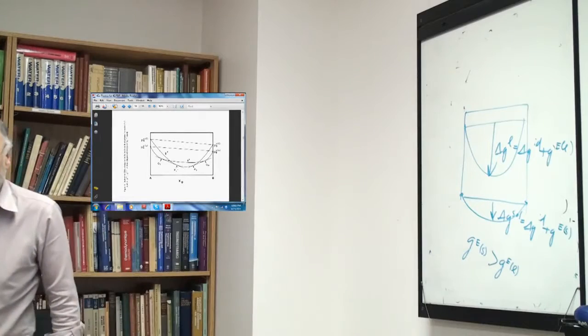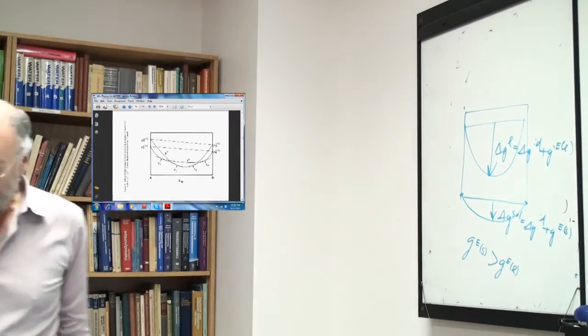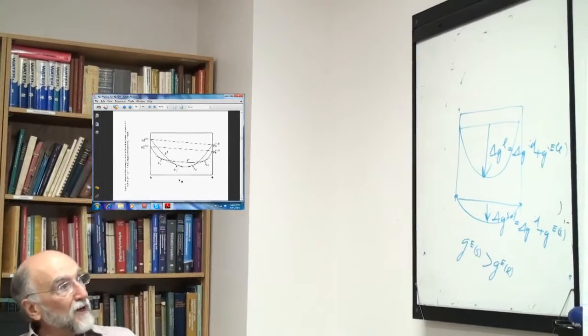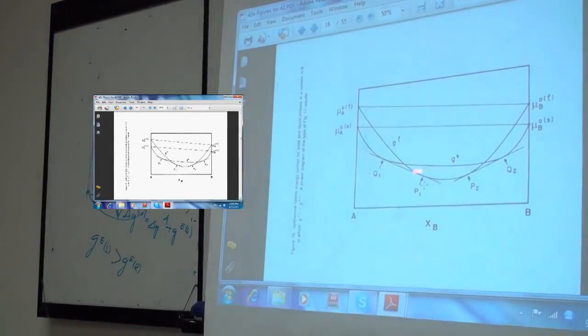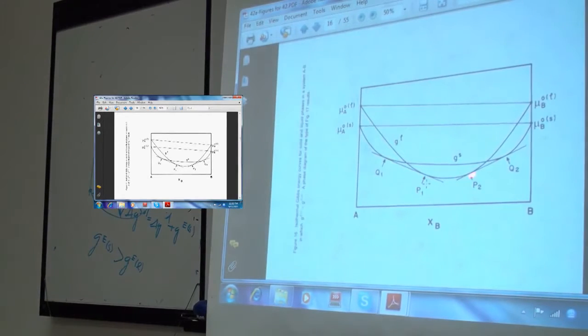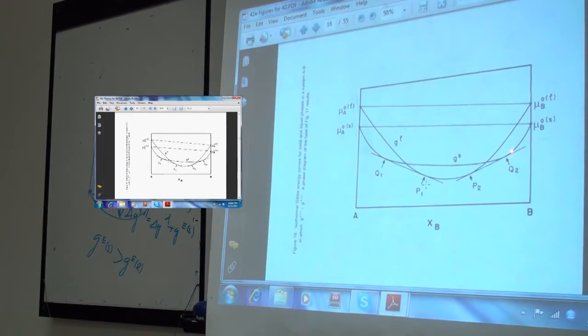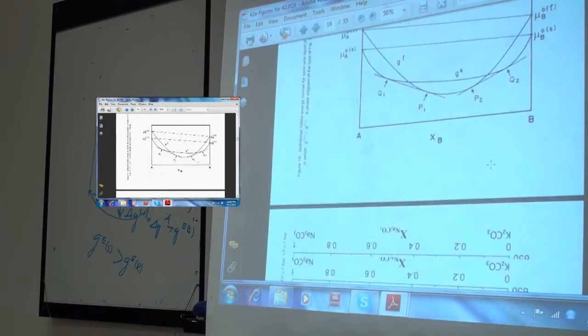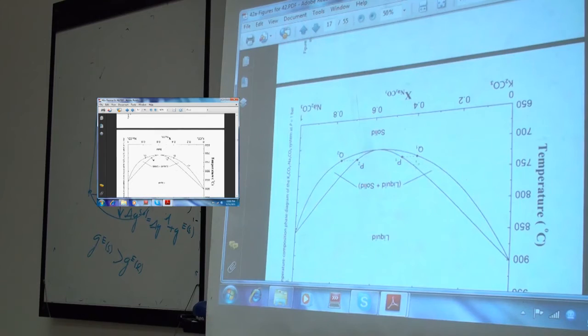Okay, so now clearly there will be some temperature when the two phases cross, as they do here. And now there will be two common tangents. There will be a common tangent on this side and a common tangent on this side. Hence you will have two phase regions, as shown in the next slide, which is now probably upside down. Okay, but there's your two phase regions.